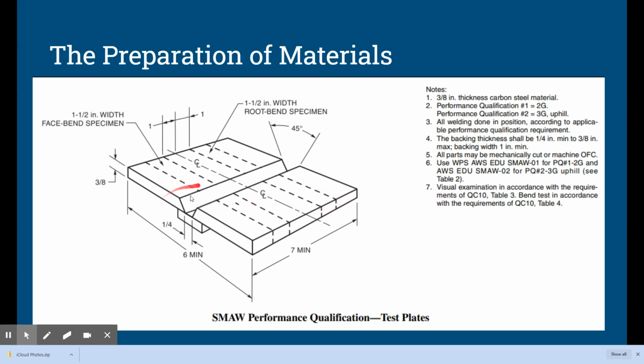For years, we did this exact same thing with both our 2G and our 3G uphill welds. We did it just like this because that's the document that SENSE gave us for a diagram on how this was supposed to be done. But further on in one of their guides, they give a technical process sheet, which gives a little bit more detail on the welds. And that actually specs out a slightly different joint for the 2G. So we switched to that. It's going to have us do a single bevel instead of a V groove. We only bevel one piece of metal with a 45-degree angle, and we leave the bottom piece flat.